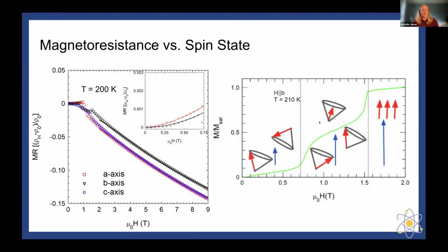Both of these are the B-axis. So the black is the B-axis on the left, the right is the B-axis only plotted. So what we see here is that when we're in this low field state, we have almost randomized spins leading to a low magnetic signal. As we increase the field, we're starting to cant the spins, so they start to rotate a little bit closer together. And then after about 1.5 Tesla, we have something that behaves like a ferromagnet.